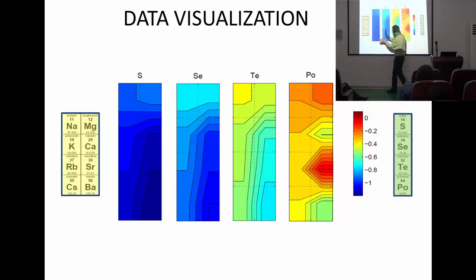The most negative formation energies, the most stable crystals, are the blue ones. So that's at the sulfur side. And the deeper you go in this group in the periodic table, the higher the formation energies become. And the red region, where you have the ones that are unstable, that will decompose in the elemental materials, they are only found in the polonium region.